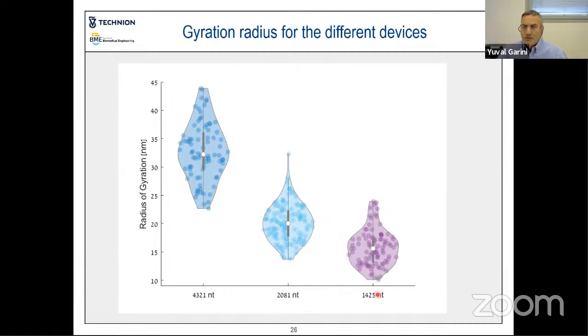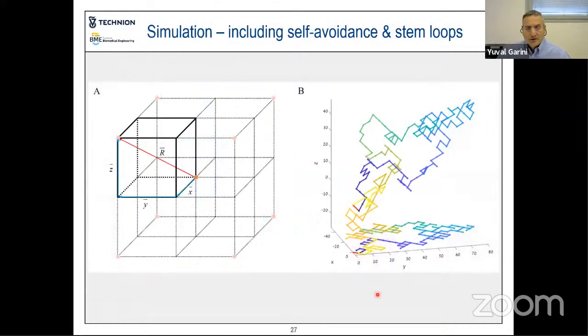And now the next point is how to fit it. So we adopted the method where we did a simulation of the single-stranded DNA. We did it in 3 dimensions, but then took only the 2-dimensional projection of the 3-dimensional structure. This is what the DNA is supposed to look like on the structure. There is a lot of literature about it if someone will be interested. Now, the simulation that we did takes into account self-avoidance. So the polymer doesn't repeat itself at any junction point. And it also takes into account the stem loops and doesn't count them along the loop, but it does count them for the calculation of the gyration radius.